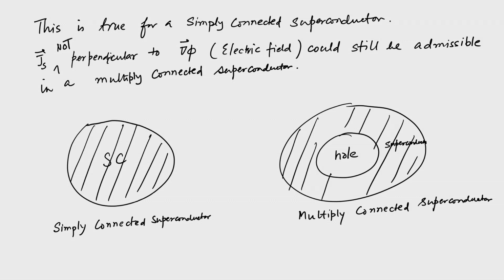So, why did we introduce this in the first place? The reason is that we wanted to show flux quantization: if there is a hole in a superconducting region, and the superconductor is called a multiply connected superconductor, put it in a magnetic field, the flux lines will thread or penetrate through this hole, and cannot take any value. It takes only values that are quantized in some known quantum, which is called a flux quantum.